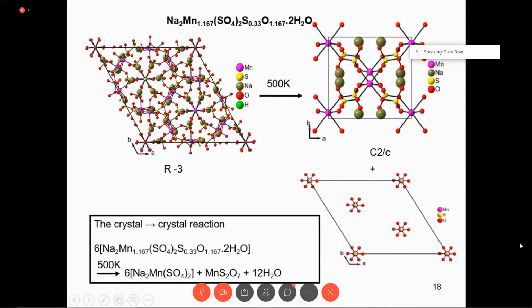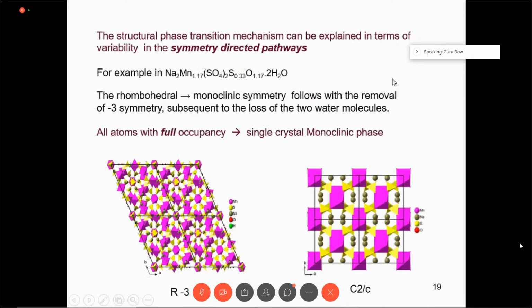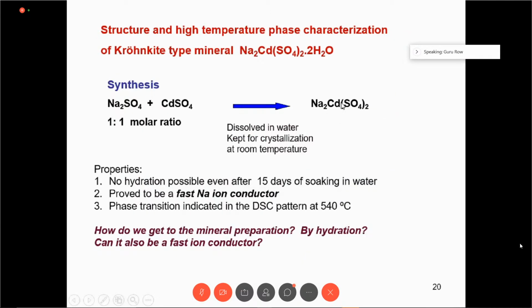In other words, what is the way in which we can make this material? We have to look for a situation where the sodium cadmium sulfate can be converted to the mineral. Can we convert this Na2CdSO4 to the mineral? So this is the first pronged approach. I told you there are two pronged approaches which we follow. The first one is the mineral formation, looking at the mineral evolution. So can the mineral evolve from these two precursors? Certainly it cannot, because as we see from the laboratory experiment, even after very long exposure and prolonged stay in water, it will not pick up the water molecules.